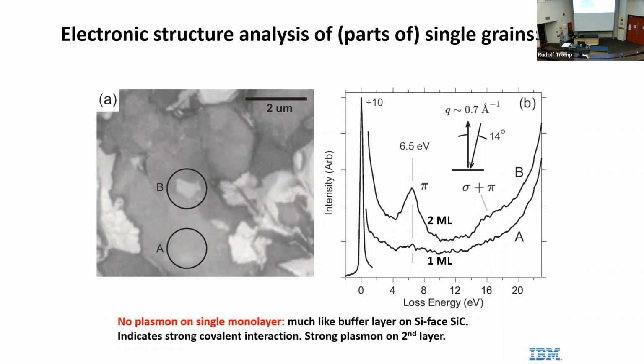That's graphene also. But that first monolayer interacts with the valence electrons in the nickel so strongly that these plasmons are completely damped. When you go to two monolayers, the second monolayer doesn't see the underlying nickel anymore. So you don't have that damping and you get a very strong pi plasmon. So just from looking at this electron energy loss spectrum, we can learn something about the electronic structure. It turns out we can learn much more about the electronic structure, which I will come to later.